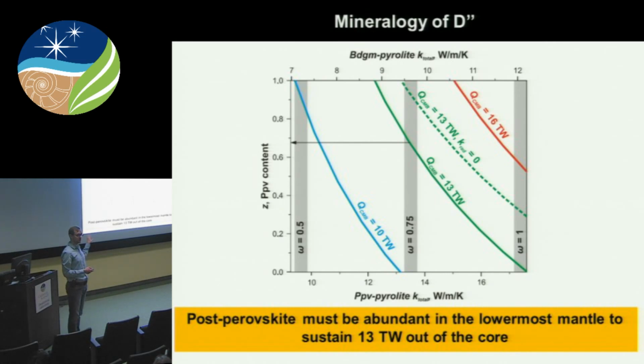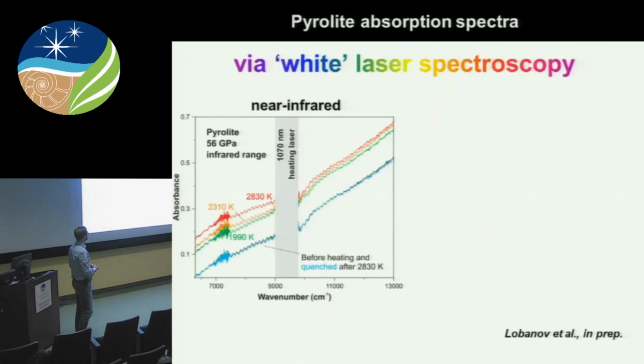And this is just a model of radiative conductivity in D double prime, which is a very important layer in our planet. So we can now take this radiative conductivity model and combine it with what is known on lattice thermal conductivity to say something about the mineralogy of the lower mantle. I don't want to go into a lot of details here. I just want to point out that the combined model of thermal conductivity in the lowermost mantle is consistent with the fraction of post-perovskite being on the order of 70%. So this is one of the takeaway messages for you today. 70% of post-perovskite is needed to have 13 terawatts of heat flux coming out of the core.